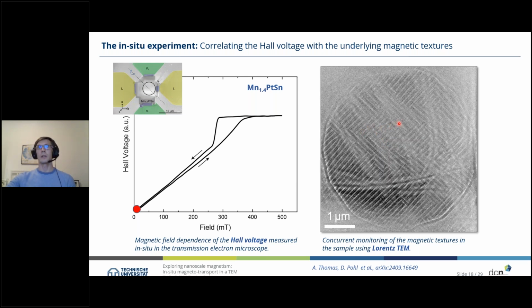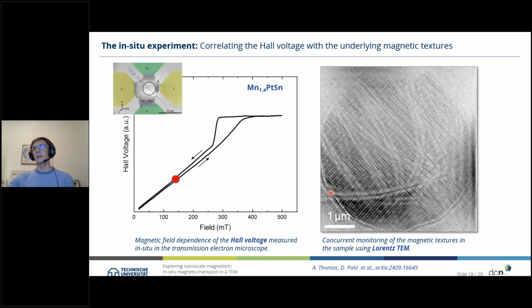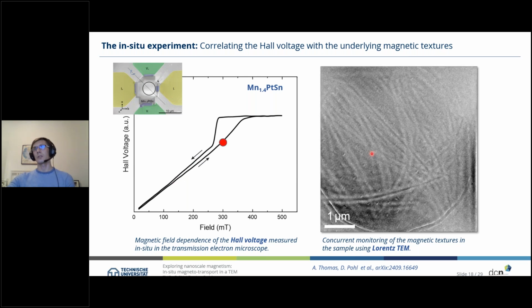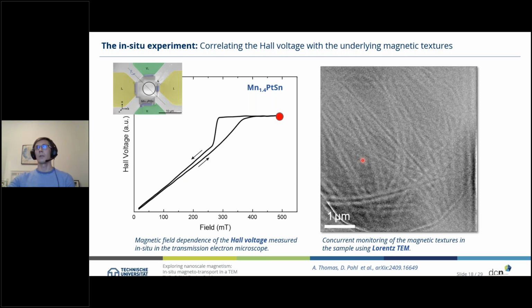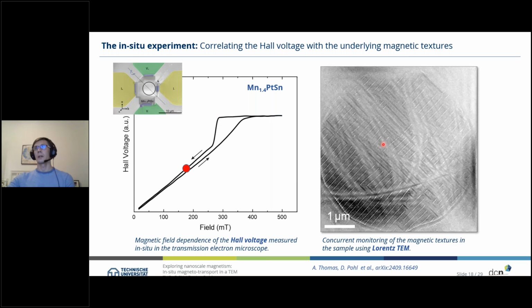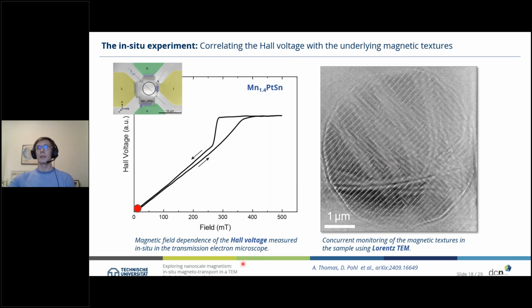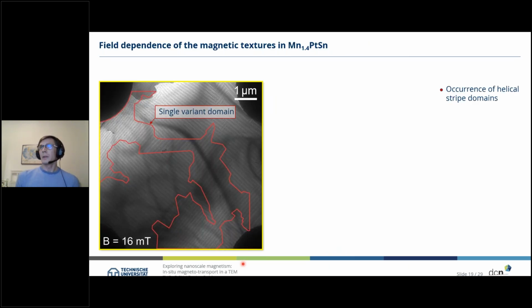Then we will have the saturation, and when we come back at a certain field value in the hysteresis loop, we will see again these stripe domain patterns popping up, going back to zero field. So you see the increase of the distance here. You see the appearance of some magnetic features. This is the saturation, only the bending contours are still visible. And there is again the stripe domain pattern. So this seems to be very dominant here, the stripe domain pattern, and we want to understand that in detail.